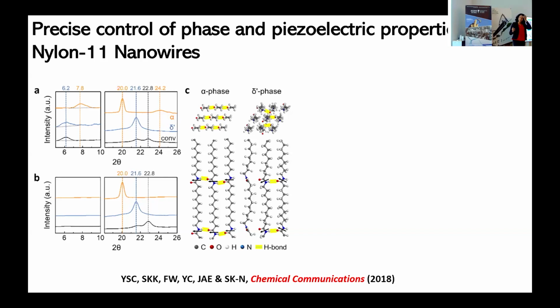And just to say, nylons have been known to have piezoelectric properties. They were studied widely in the 80s and the 90s, but then their properties weren't as good as say PVDF, so they kind of died out. Also, they're hygroscopic, so not very stable. But we found that when you grow them in this technique, you can actually access phases that are not accessible in thin film or bulk form. For example, this so-called delta prime phase.